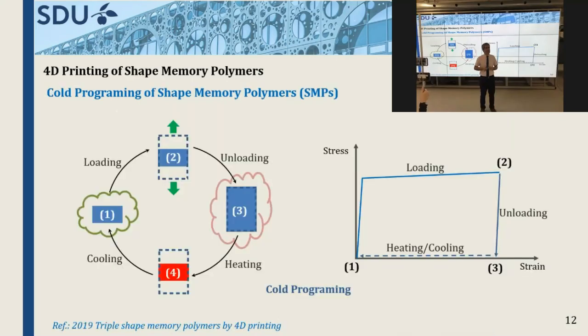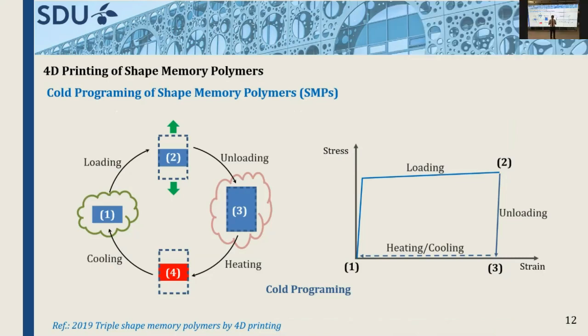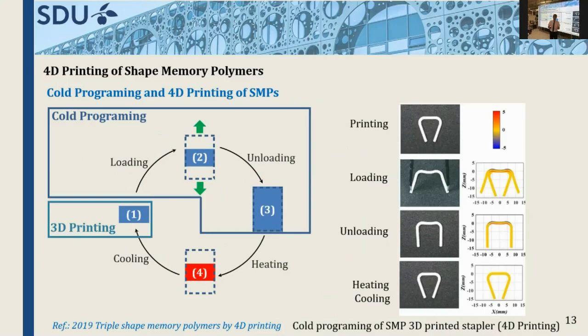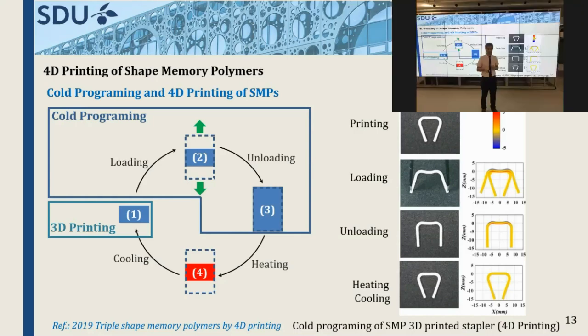The other feature of shape memory effect in shape memory polymers is the cold programming. It means that the material at room temperature experiences loading and unloading, and we achieve a new configuration. This configuration can be recovered by heating and cooling process. It means that we can print the structures. After that, we can change the shape to the desired geometry. This desired geometry can be recovered by heating and cooling process. As you can see, this cycle is shown as a stapler in the right-hand side picture.